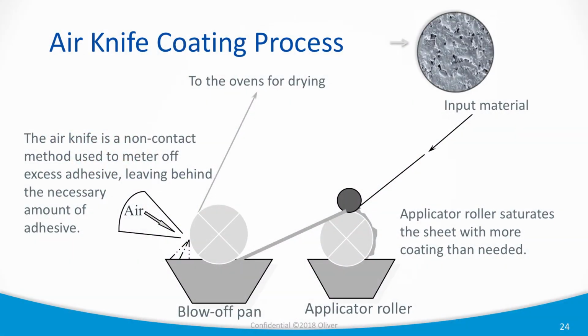Okay, the other process is for water-based adhesive, and again, think the adhesive is carried by water. It's somewhat similar to a latex paint, but basically you have material coming into the applicator roller, which is picking up adhesive, laying it down on the bottom of the substrate, and then you have what's called the blow-off pan. And basically, an air knife is a non-contact method. Think of it as using air as a doctor blade. Basically, you're blowing off excess adhesive into the blow-off pan. So that's what's controlling your coating weight. By controlling the air pressure in the air knife, you control your coating weight.